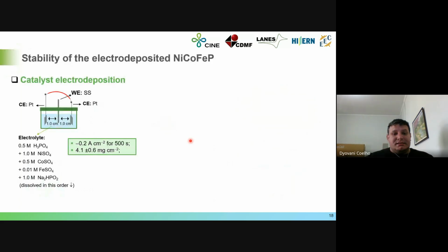So the catalyst is electrodeposited in a galvanostatic regime, applying minus 0.2 amperes per square centimeter for 500 seconds, which produces a catalyst loading of around 4.1 milligrams per square centimeter. The catalyst electrodeposition bath is composed of the metal precursor sulfates, and as a phosphorus source, sodium hypophosphite is used.